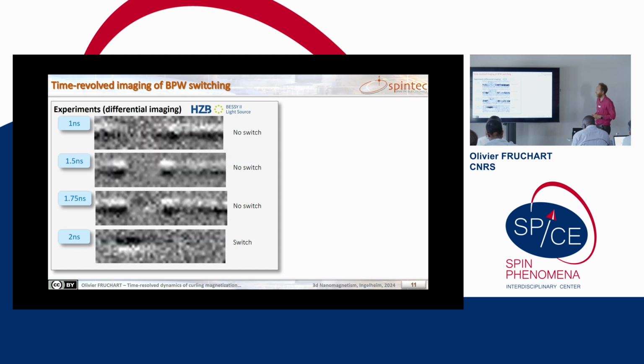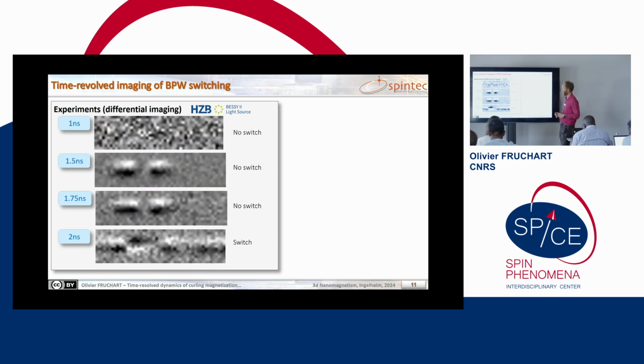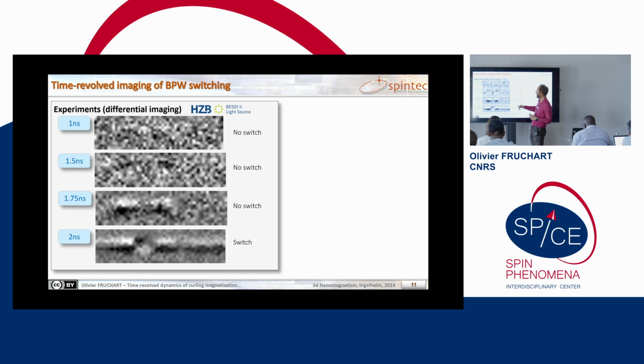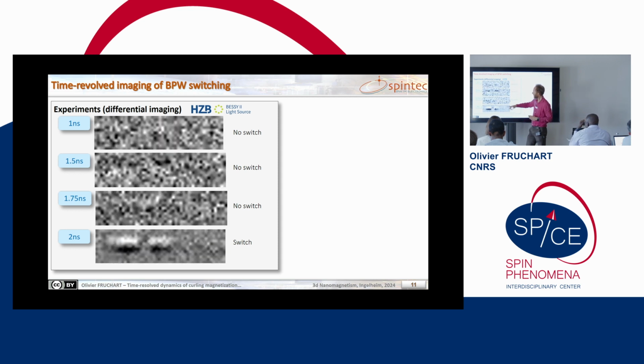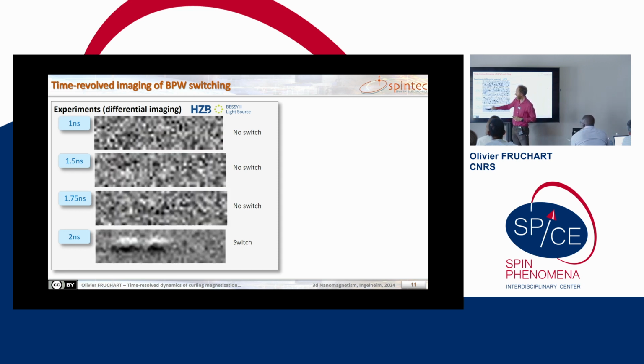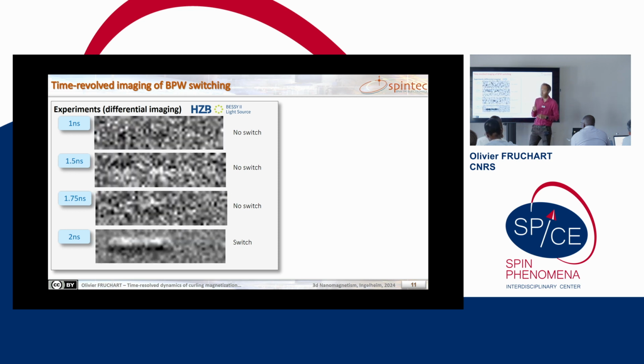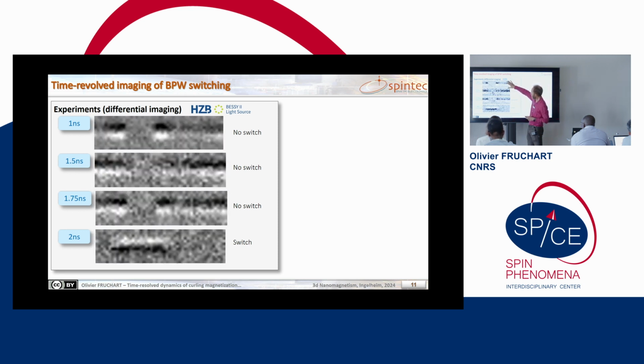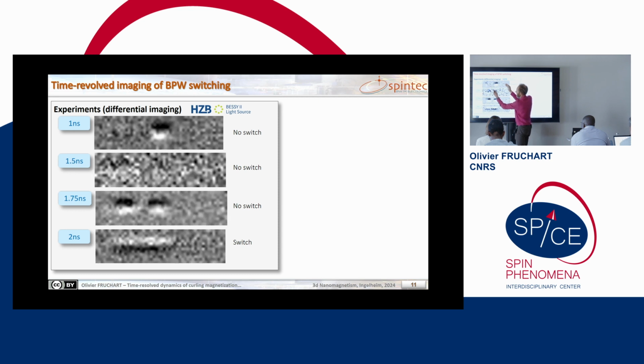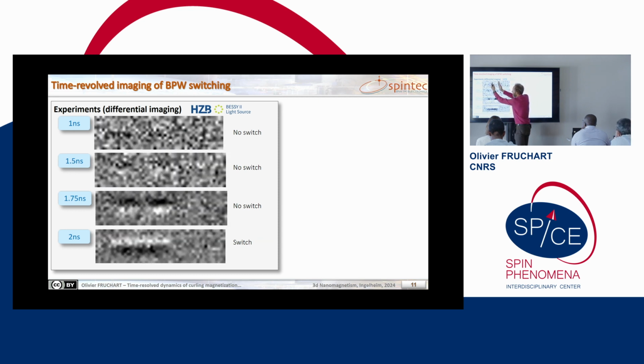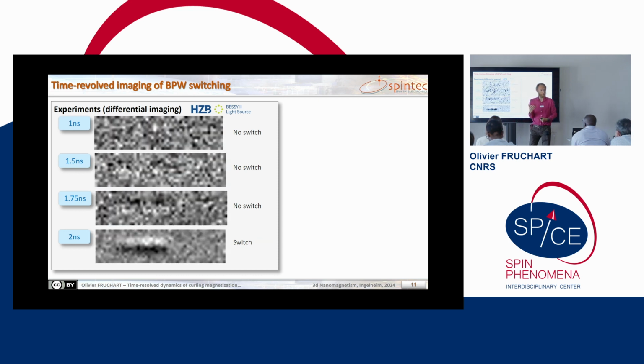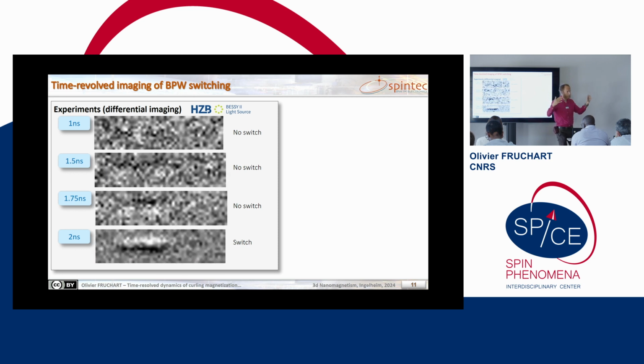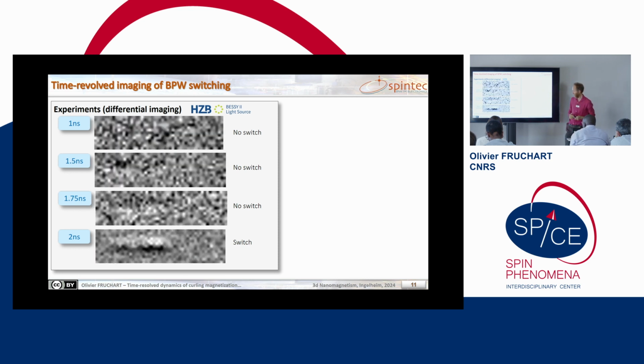So the funny thing now, you can make some time-resolved measurements. This was done at BESSY. And for instance, this is as a function of the length of the pulse. And here you see that it is differential imaging. So the domain wall shrinks, but the pulse is not long enough. And then when you remove it, the domain wall goes back to its initial size.